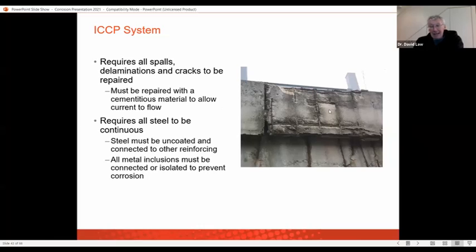To be successful, you need to repair all of the spalls and delaminations to ensure that the current circuit can be set up and those anodes on the surface work. You also need to make sure that you've got all your steel connected into the system, or it will be corroded if it's not connected into the system. And you also need to make sure that your concrete, the original and the repairs, allow current to flow. So you don't really want polymer modified concrete in there, because that's going to make it a lot more difficult to actually pass the current through your concrete.